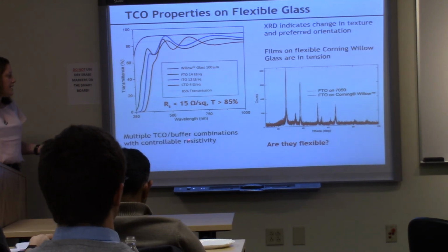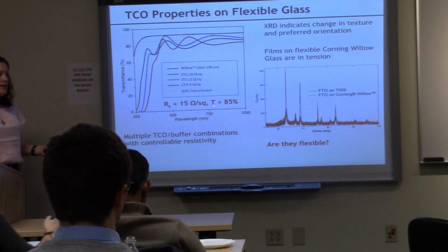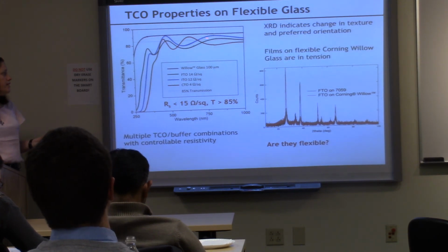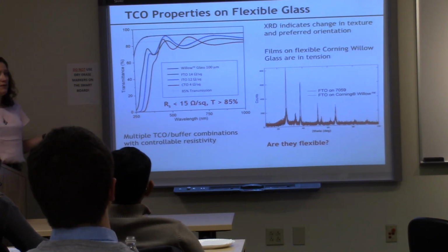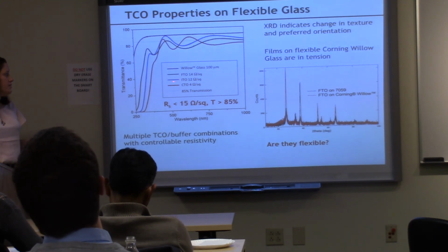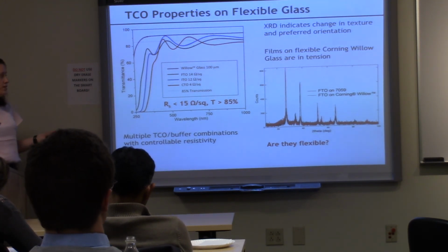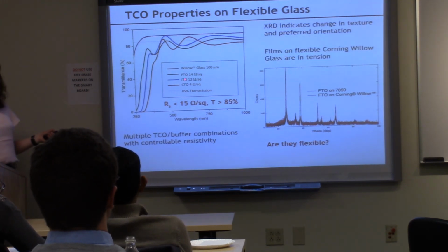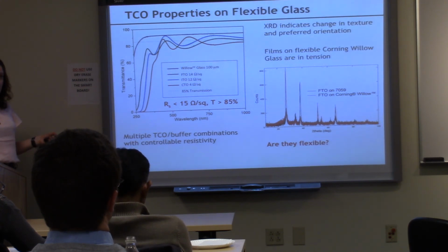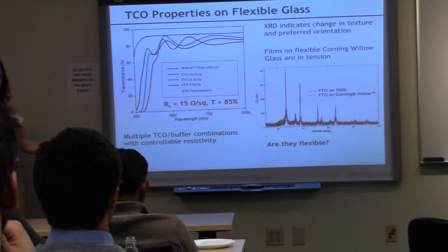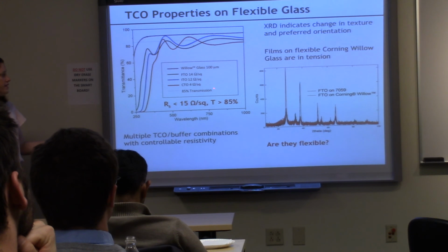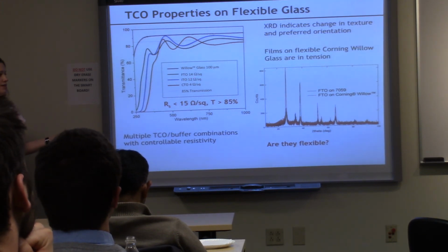So the first question we had is, can we meet this very basic metric for a transparent contact for a CdTe cell, of a resistance below a 15 ohm per square threshold, and transmission above 85 for a lot of it? And the answer is yes. We met that with a variety of different materials. We did it with tin oxide, which is the standard contact in CdTe, indium tin oxide, which is a standard display material. We use this even though we don't use it in CdTe, because this is the thing that is the gold standard for TCOs and is determined to be brittle.